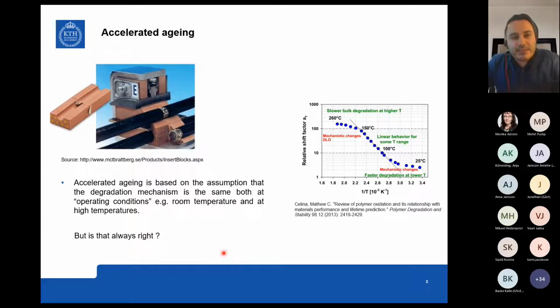So when you do accelerated aging, it's really evident that you need to plan your experiments and tune them so that you're mimicking more or less the conditions and boundaries of the application. But at the same time, you still need profiling tools where you can assess your material and see, at these high temperatures or high dose rates, how the material has actually changed and been altered.